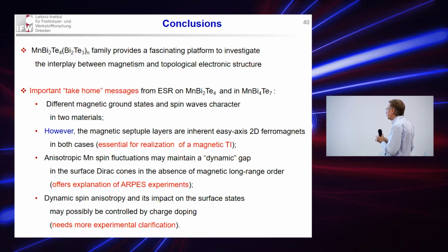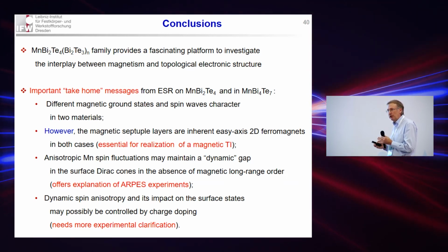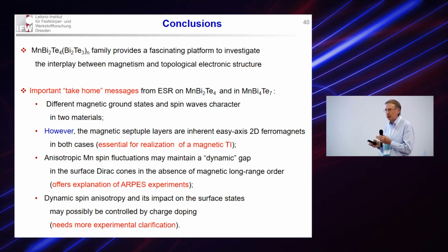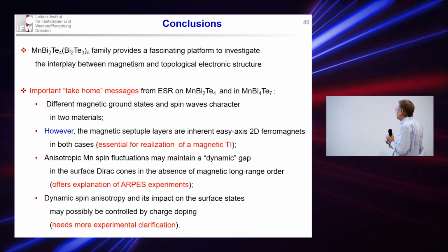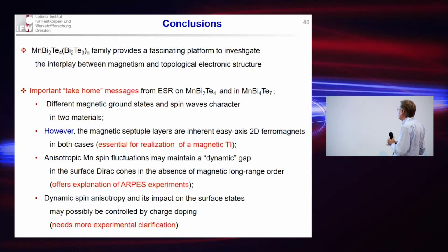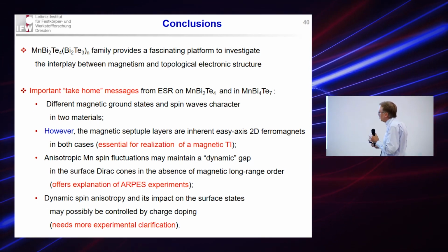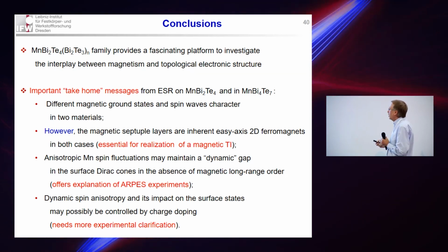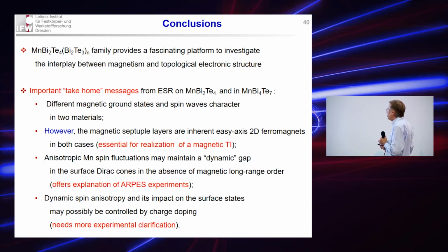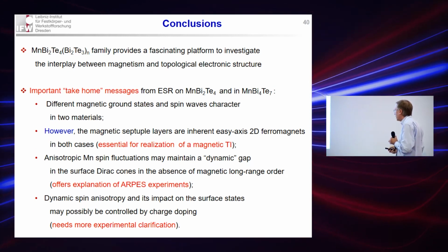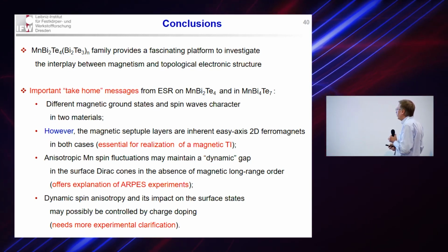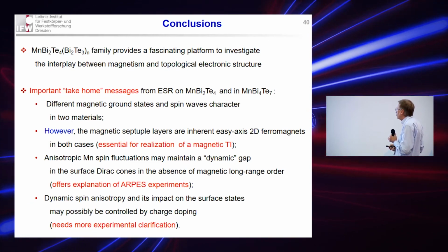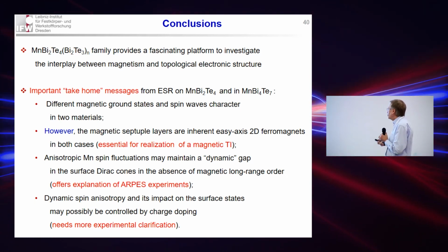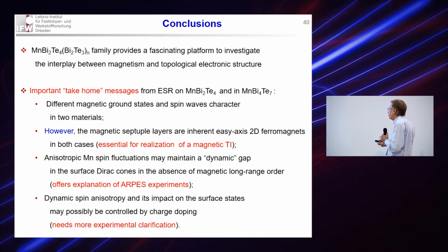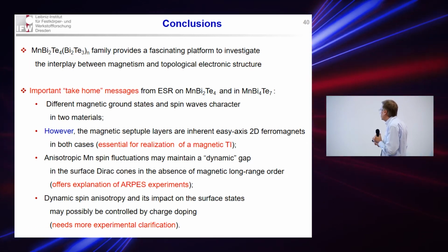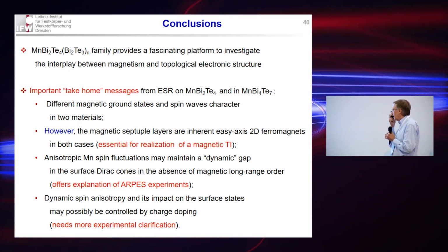However, if we extract the specific properties of the magnetic building unit, the manganese bismuth 2 tellurium 4 layer, it turns out that it really has an inherent easy-axis two-dimensional ferromagnet property in both cases, and we can generalize it to other members of this family, which is essential for the realization of this magnetic topological insulator. Another interesting observation is that we found a strong anisotropy of the manganese spin fluctuations in the disordered state, which helps to maintain a kind of dynamic gap on the surface cones, even in the absence of the magnetic order, which could explain our ARPES experiments.